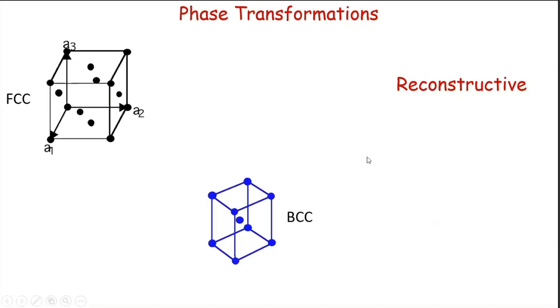And what you mean by reconstructive transformation is that all these atoms are ripped apart, they diffuse through the lattice, and you reconstruct it at some nucleation site, if it's a heterogeneous site, at some particular choice or site which is preferred over others. So you reconstruct the whole lattice, much like you take the house and tear it down and reconstruct the whole house somewhere else using the same materials. Well, that would be the reconstructive transformation.